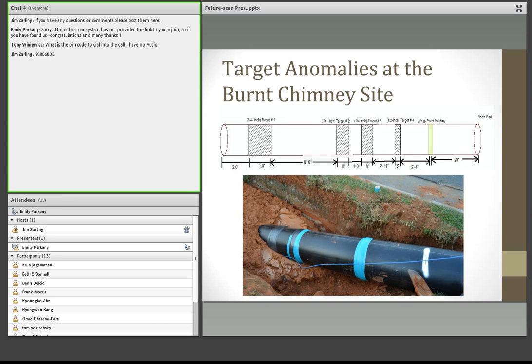There were 4 different voids. The first one was the largest. It was a foot in length and about 1/4 of an inch thick. The two in the middle that you see were a little smaller. They were each 6 inches in length and both a quarter of an inch in thickness. And then the last void that we installed was the very smallest, and it was 3 inches in length and a half an inch thick. And you can see from the picture below that after we wrapped this foam around the pipe itself, we loosely covered it with duct tape so that it would stay secure on the pipe as it was pulled down into the ground when the pipe was installed.